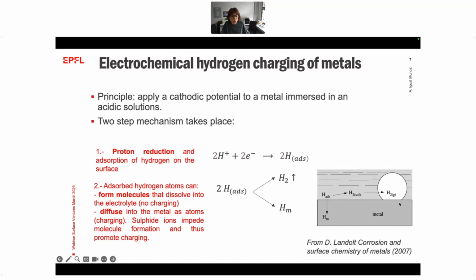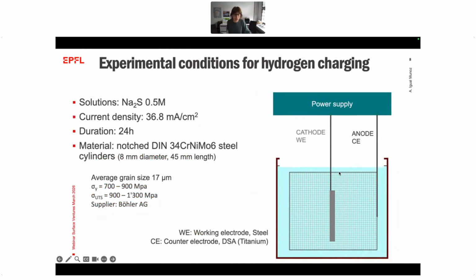What the adsorbed hydrogen does on the surface will depend on several factors: surface factors, electrolyte, and also polarization conditions. What we did is a very simple charging. We use a sodium sulfide solution, because certain species like sulfides inhibit the recombination of the hydrogen. So with this solution, we are favoring the hydrogen intake into the material. Then we just apply a certain current with an inert anode. Typically, we took a dimensionally stable anode, typically titanium covered with some coatings. And then the cathode is the material we want to charge with hydrogen. In this case, it was a steel.